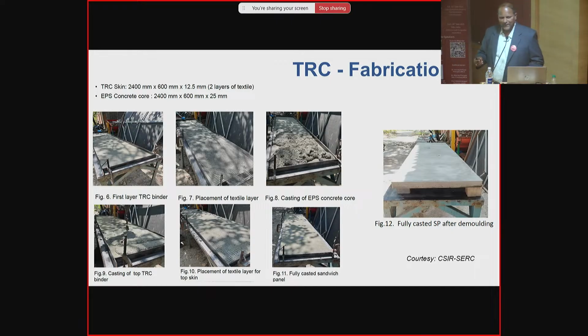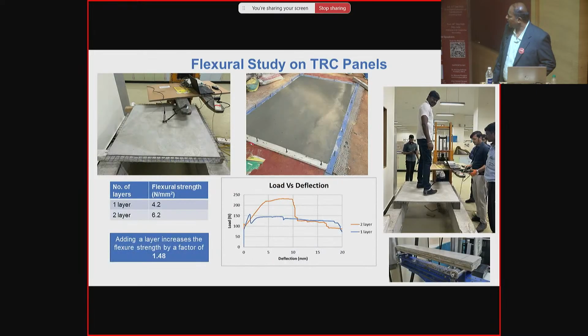The TRC elements, typically, can be made as thin as 15 mm, and can go up to around 40 mm, exactly similar to ferrocement. Now you can see here, this is the ferrocement, which has a thickness of around 25 mm.